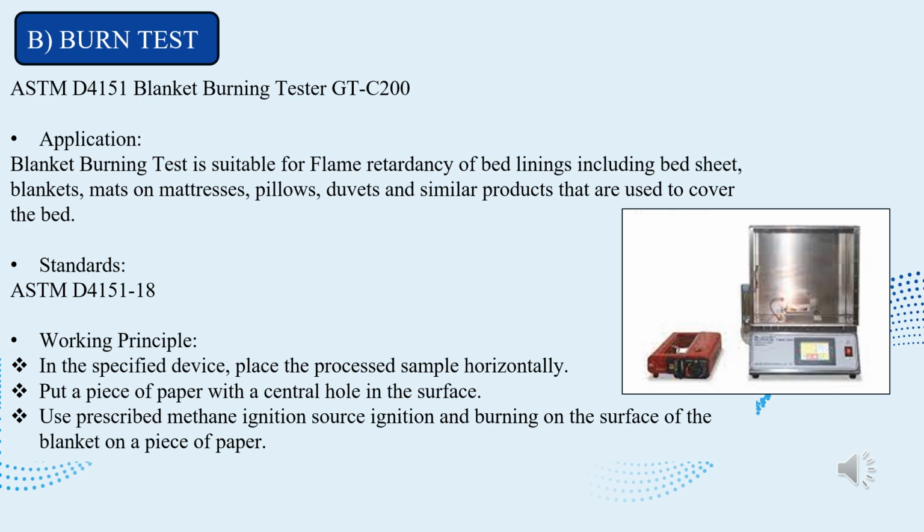D4151-18. The working principle: in the specific device, place the processed sample horizontally. Put a piece of paper with a central hole on the surface. Use a prescribed methane ignition source and burn on the surface of the blanket on a piece of paper.